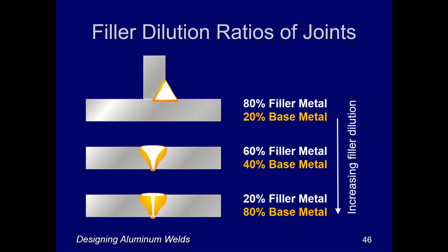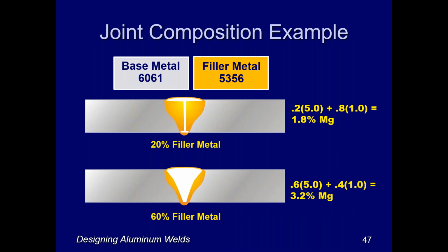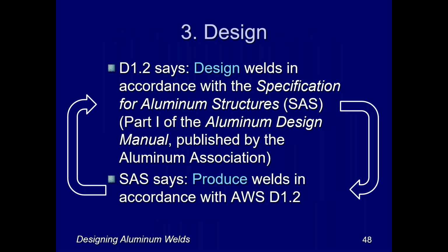And so these are things that are important to keep in mind, and therefore what filler metal might work for a fillet weld might not work very well at all for a square groove weld in terms of cracking sensitivity. And the way the composition of the weld metal is calculated is simply based on how much dilution you have and what the composition of, say, the magnesium is in the base metal and the filler metal, as I show in this example here. A square groove weld or a V groove made in a base metal 6061 with filler metal 5356.